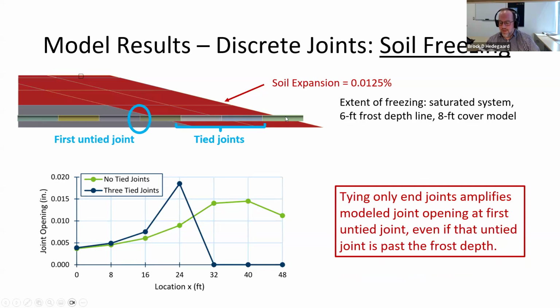So by tying them, it just means we fixed them. So this is sort of a mix between our continuous pipe model and our discrete joint model. We got 4 continuous segments here that are all tied together and 1 untied joint. As we can see in the results down below, even though that untied joint is past the frost depth, you'll find that the total motion of that embankment pulls all 4 of those units of culvert, or all those lengths of culvert, out together, and it concentrates your separation in one particular location.